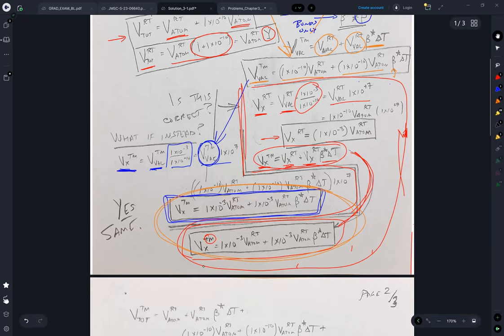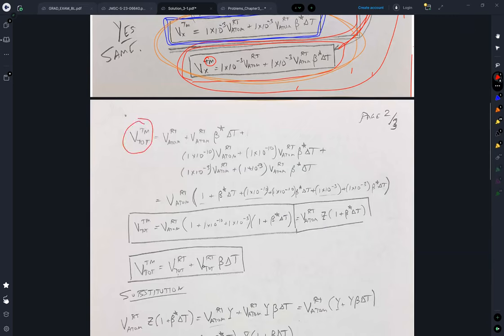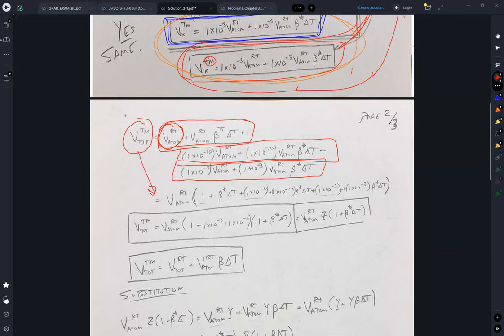So if I do that, now I can express the total volume at the melting temperature in terms of the atoms at the melting temperature, plus the vacancies at room temperature, plus the extra vacancies at room temperature. And all of these terms are in terms of the volume of atoms at room temperature. So I can take and simplify, pulling this term out.